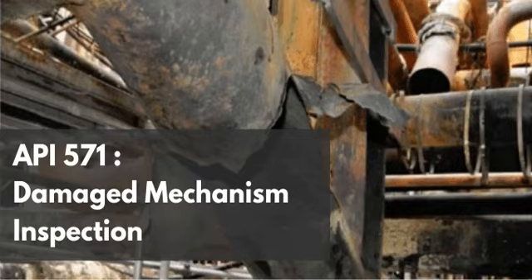Yeah. You take the coupon you cut out of the tray or the pipe, you put it in a hydraulic press or a vise in the lab to simply bend it over a mandrel. And instead of folding and yielding like steel should, it just forcefully snaps. Wow. That sudden audible snap in a simple bend test is your definitive confirmation that the alpha prime phase has taken hold and 885 embrittlement owns your equipment. Exactly. It is the ultimate proof of the microstructural degradation.